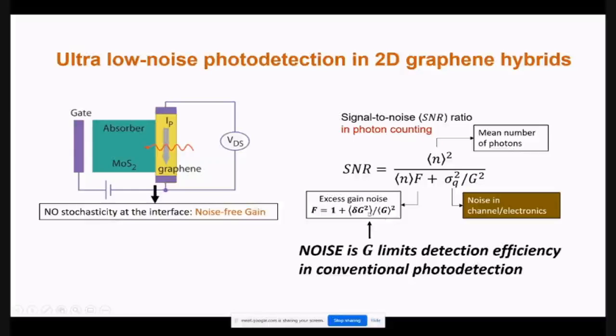F is called the gain noise, in which there is an optical gain that you have when you shine light, and the other is noise in electronics. Usually these two degrade the performance of a photodetector. Normally in the case of a graphene MoS2 photodetector, unlike standard single photon counters, this F is 1, or the gain noise is 0, simply because the flow of current is physically separate from where the absorption of light takes place. Absorption of light takes place in molybdenum disulfide, and the current flows through graphene, which is why F is actually just 1. So we are usually dominated by the noise in electronics, which is determined by the dark current. Okay, and if we can operate this at a very low dark current, we will be able to measure even single photons, and that's the plan.